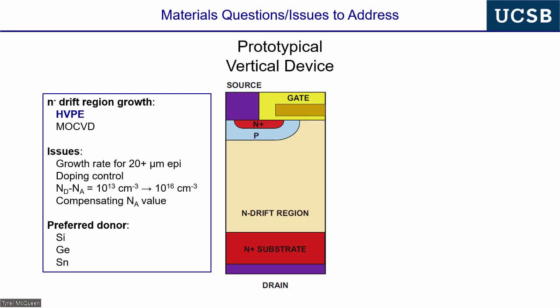That means 200 volts per micron. Okay, so a kV is 5 microns, 10 kV is 50 microns, 20 kV is 100 microns. So suddenly we need exceedingly thick epitaxial layers, okay, that have sustained outstanding morphology, and uniform doping. Okay, and so the preferred technique for having really thick drift layers is hydride vapor phase epitaxy, okay? And so far, this only goes so-so for gallium oxide.